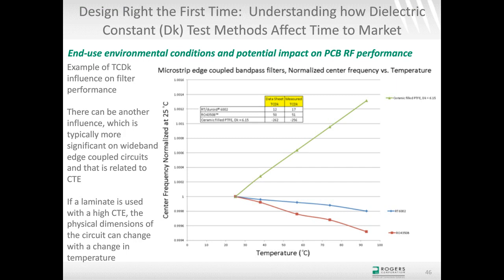And you can see the materials with the better TCDK of about 16 or 17, the RT/duroid 6002 materials, that's the blue curve, not much difference there. The red curve is the RO4350B materials, a little bit higher TCDK around the range of 50, which is still considered good. And you can see there's not much difference there, actually.